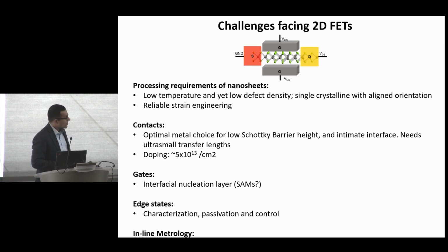Now, if you want to do direct growth, you need to have a low temperature process. You need to be able to get low defect densities. I genuinely believe you need to have single crystalline patterns. The orientation of all the sheets needs to be well aligned. And the reason why the orientation needs to be well aligned is not because of mobility, not because one has a higher mobility than the other, but because of the edge states. Depending on the orientation, you will have different edge states. Some are metallic. And this is really problematic, especially when you make the sheets very narrow.